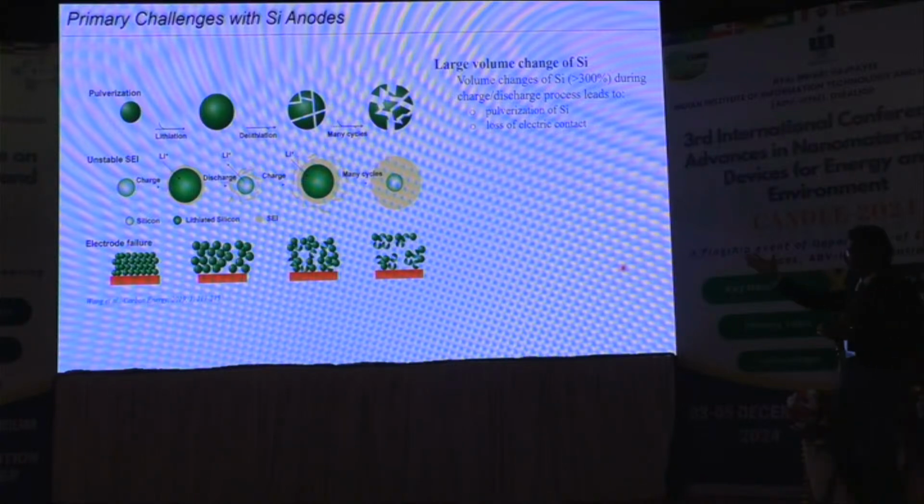And the 300% volume expansion then leads to pulverization, because every time you start with the silicon atom, let's say here, or silicon compound, lithium silicon compound, you lithiate it, delithiate it, and it just keeps fracturing, right? And then there is another important parameter which I haven't mentioned at all. It is called the solid electrolyte interphase, SEI, and I won't have time to talk about that, but SEI is very critical for stable operation of a battery.